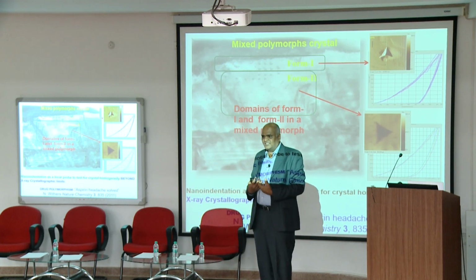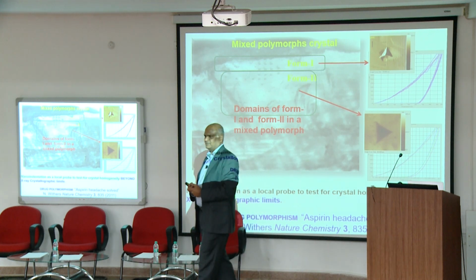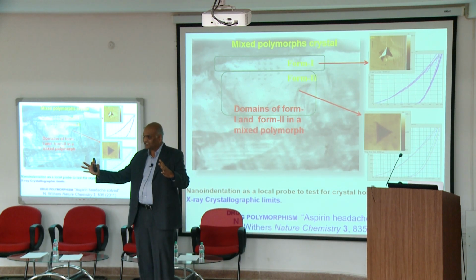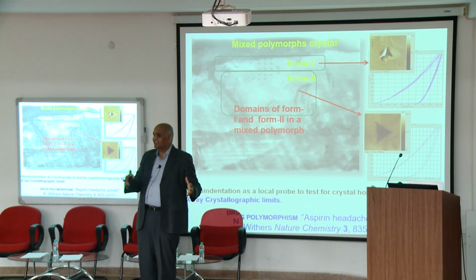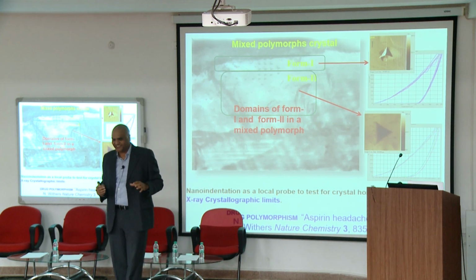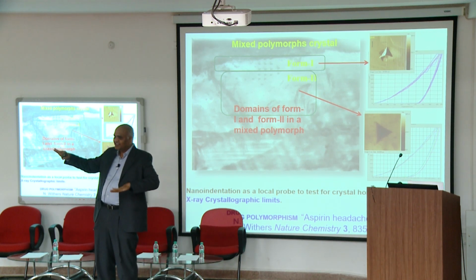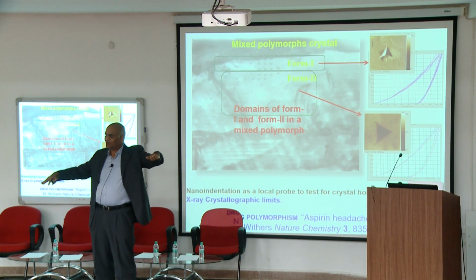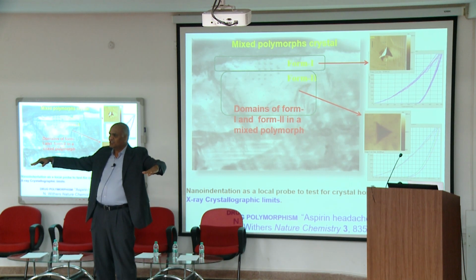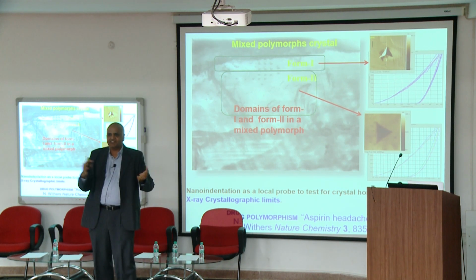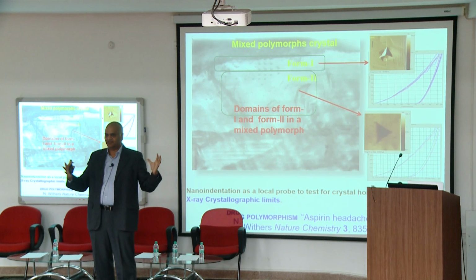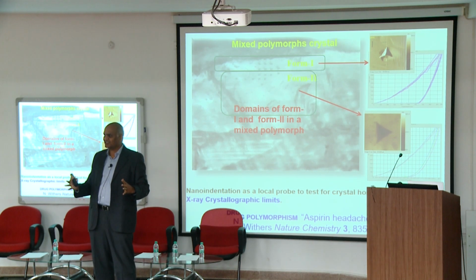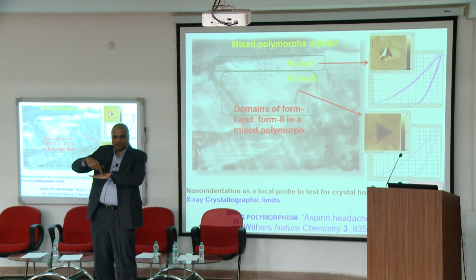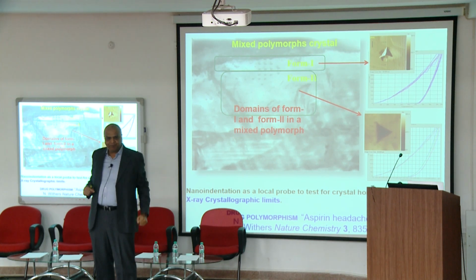Some other domains, you get a different response, right? So because there is this intergrowth polymorphism, you think it's one crystal, right? It's like Ardhanarishwara, maybe some way. The thing is, you think it's one crystal, but in one domain it's form 1, and in one domain it's form 2. So when you do Xray diffraction, you get a mixed signal of all this, because even if you take microfocus Xray. With nano indentation, because we are poking locally, you're getting different responses, okay?